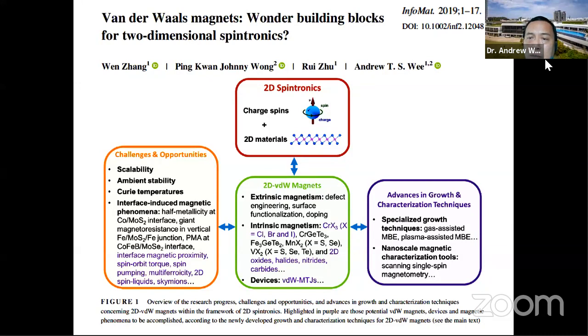On the right, it shows that some of the challenges in this field is there's a need to be able to grow large area films in order to scale up your devices. And one technique which we will use and is particularly useful is MBE, because not only can you grow these films in very clean conditions, you can grow them controllably at the atomic layer thickness. And then there are the tools you can use to characterize them. There are many of these magnetic tools, but they have to be sensitive to the monolayer level. So that's the challenge of this field.